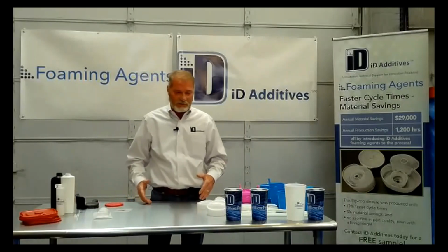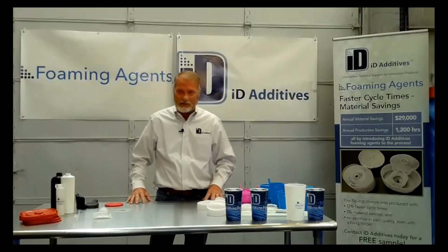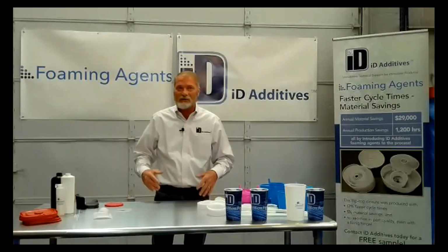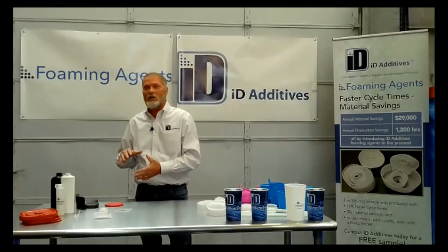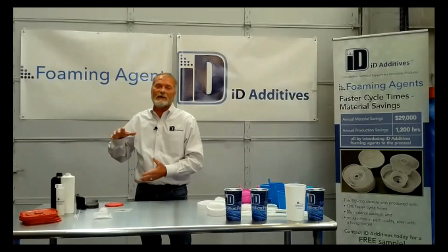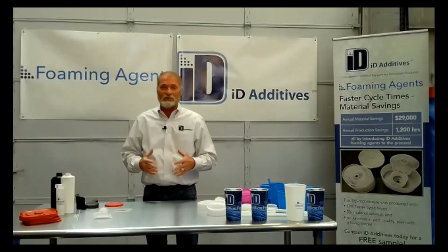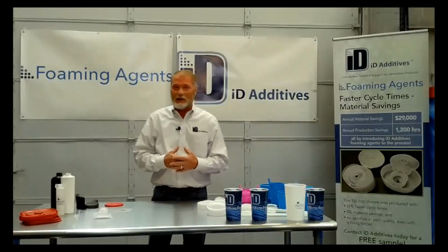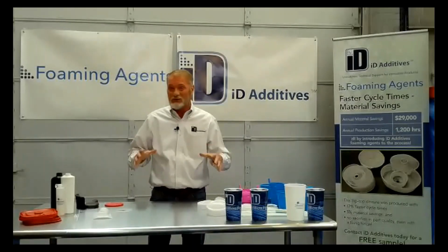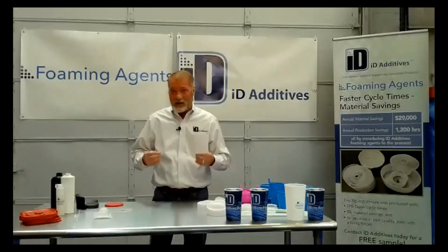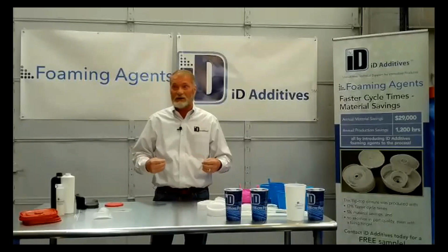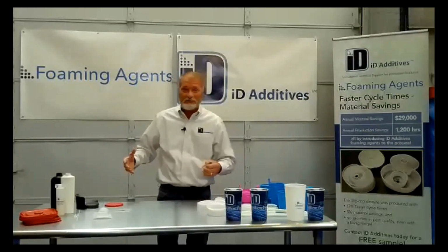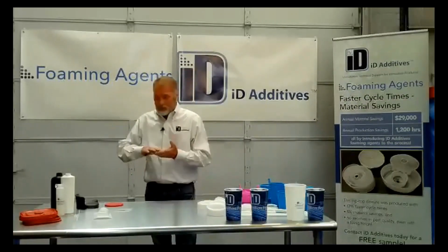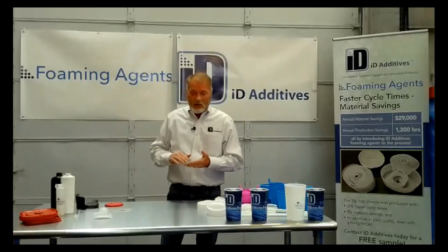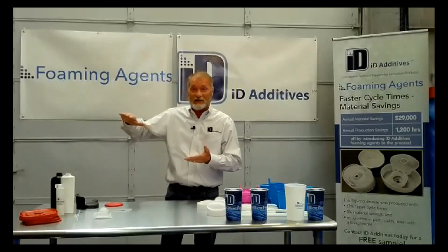So injection molding, again, speed is the thing to do. Rear zone's cooler, and the reason I like rear zone's cooler is that it keeps the foam from pre-foaming in the rear. Now, really, you are going to lose gas. I mean, no matter what you do, you're going to lose gas. But you want to optimize that gas so you don't lose as much. So rear zone's cooler. Endothermics, they go off in a slope. You want your temperatures to reflect that.